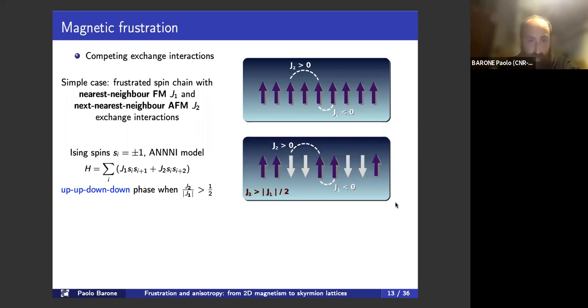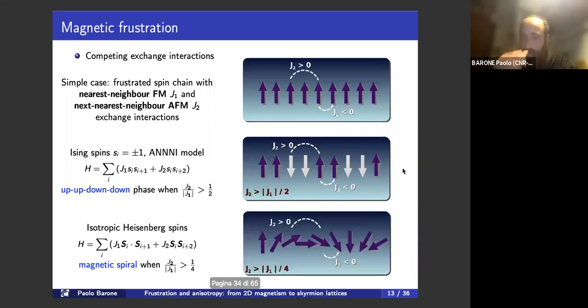And then depending on the ratio between the two competing interactions, we can have some exotic spin configuration. So for instance, if we have again just Ising spins with these competing interactions, when the antiferromagnetic second nearest neighbor interaction is larger than half of the ferromagnetic one, we can stabilize this peculiar up-up, down-down phase, which, by the way, breaks the inversion symmetry of the lattice. And this has been proposed, for instance, in the beginning of the multiferroic field.